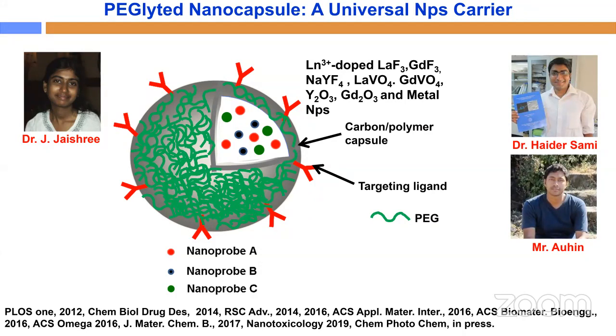Within the cavity of the carbon or polymer capsule, we have synthesized lanthanide-doped nanoparticles, for example lanthanum fluoride or gadolinium fluoride, or any particle which we can load inside. Another advantage here is that we can load multiple types of nanoparticles. For example, lanthanide-doped lanthanum fluoride can give you the fluorescence emission, and lanthanide-doped gadolinium fluoride can give you the magnetic resonance imaging property. So we can do fluorescence imaging as well as MRI imaging.